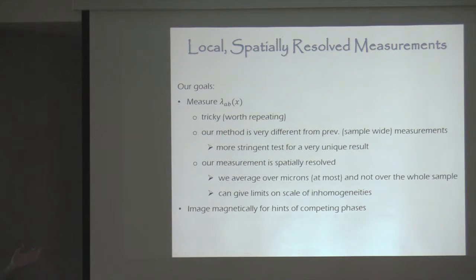The most notable thing is that we don't sample over the whole sample. So our measurement is spatially resolved on a scale that's not worse than microns. Maybe down to 1 lambda. We don't need an area that's more than a few microns wide. That is worthwhile, and then you can maybe get information about heterogeneity and stuff like that. And finally, we can do imaging, and so we can maybe get hints of other phases that exist.